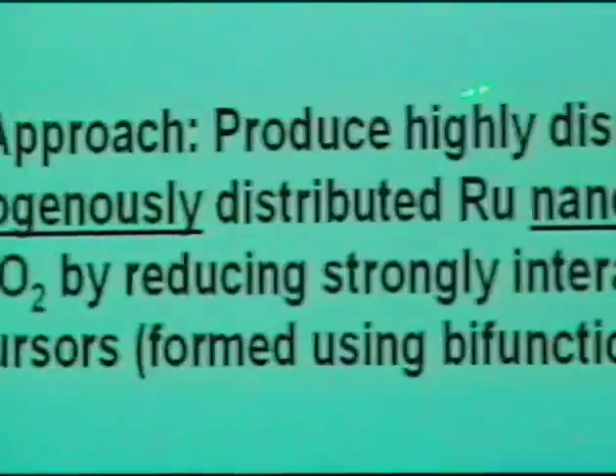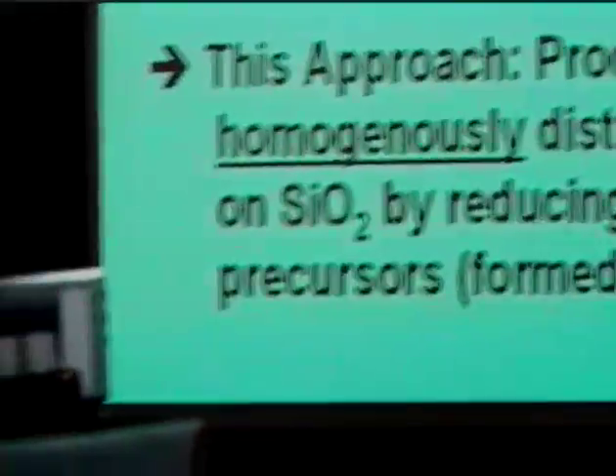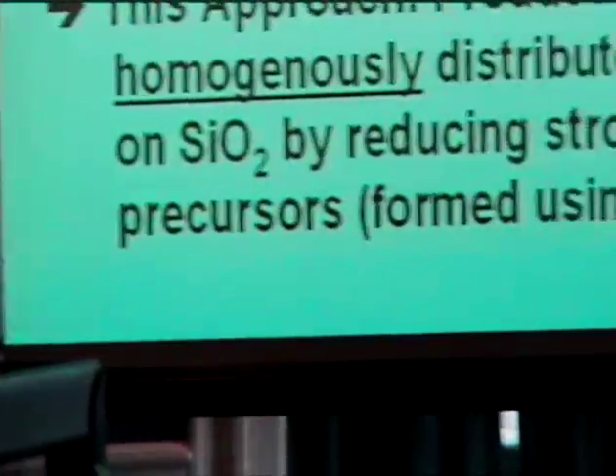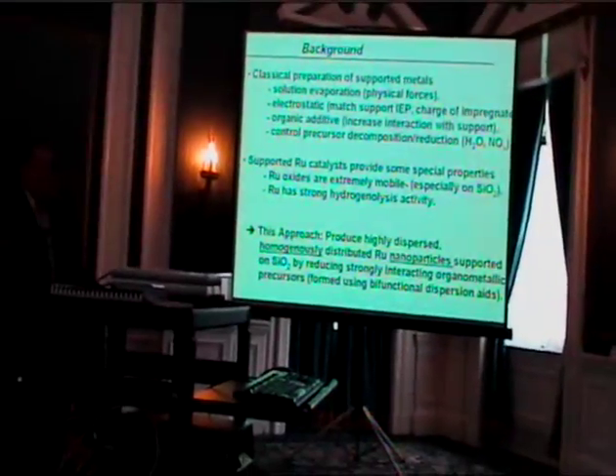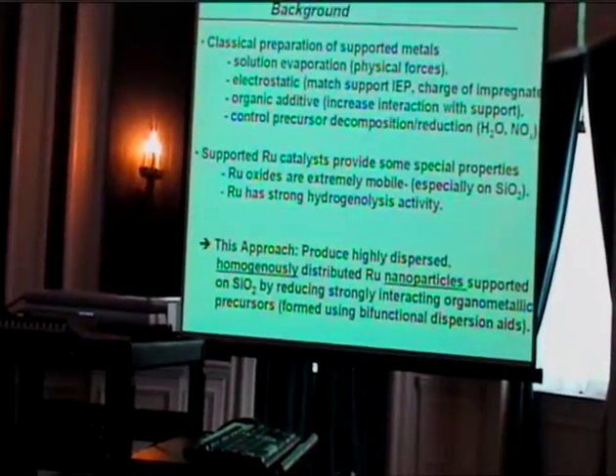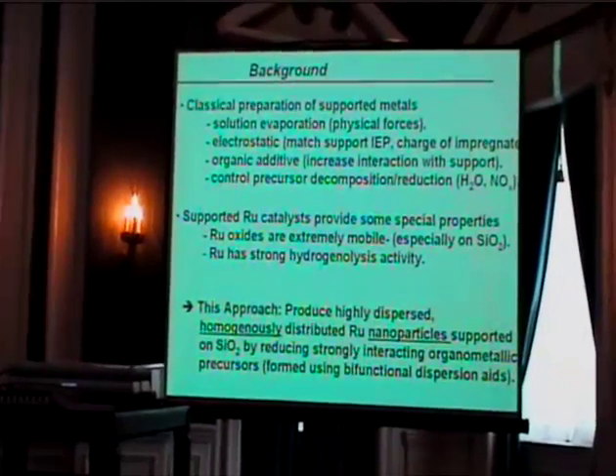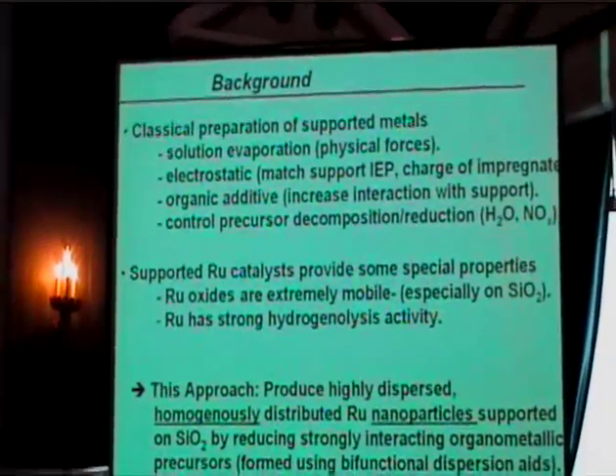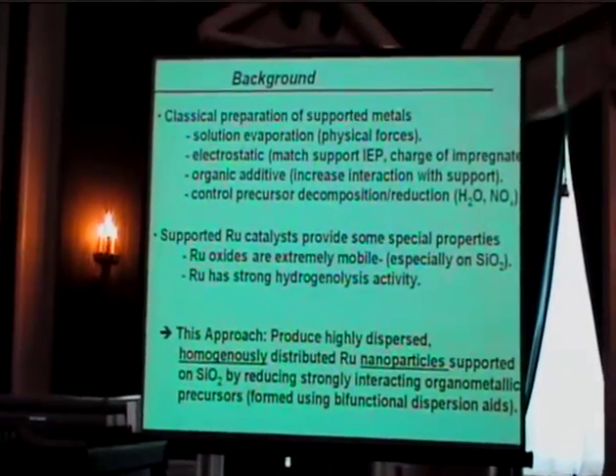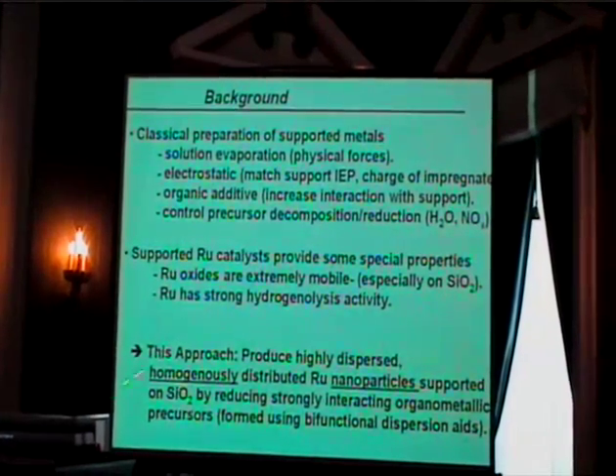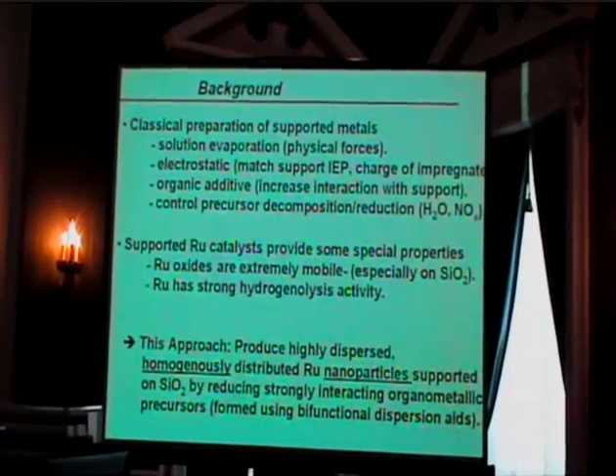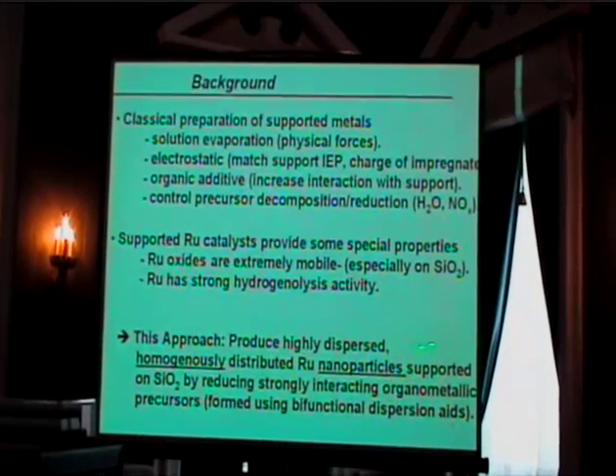And what I'm going to try to show you is that in this approach, what we've been able to do is to produce highly dispersed, not only dispersed, but this sort of factor on supported metal catalyst, which many times I don't believe is very well appreciated, but we find that we've had many situations where this actually turns out to be quite important, that not only do you want it dispersed and small, but you want them homogeneously distributed on a nanoscale on that support. You don't want clusters, you want them nicely distributed, and we're going to have some examples of how you can have catalysts that at least look the same in some ways, but because the nanoscale is different, they behave very differently.